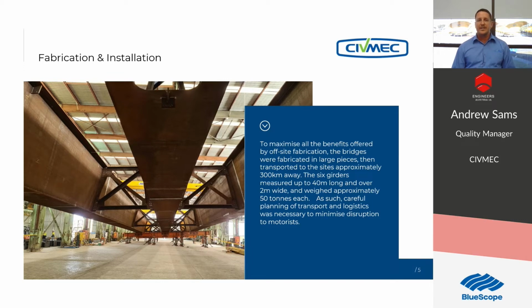The girders were fitted and assembled, and the site splices tacked to capture accurate measurements and dimensional tolerances. It also ensured that the site weld fit-up was correct. All welding on the bridge was done by qualified personnel using WPSs. The bridge was surveyed by two independent contractors, and the RMS team also came out and did a 3D scan of the bridge.